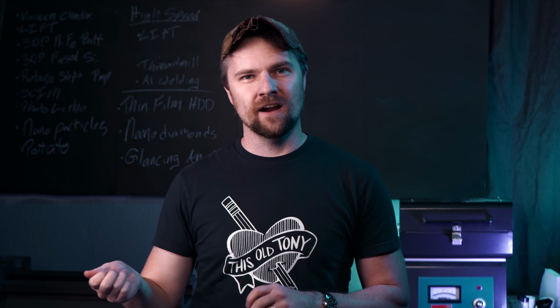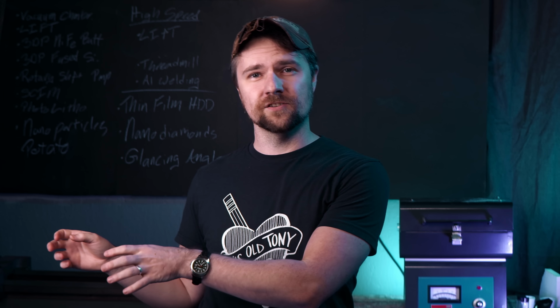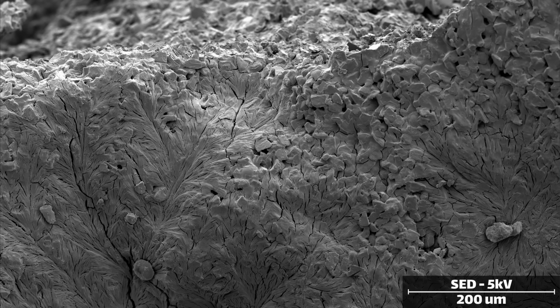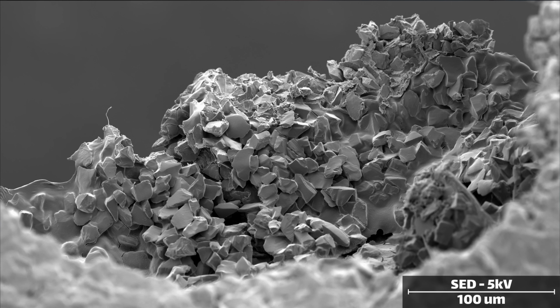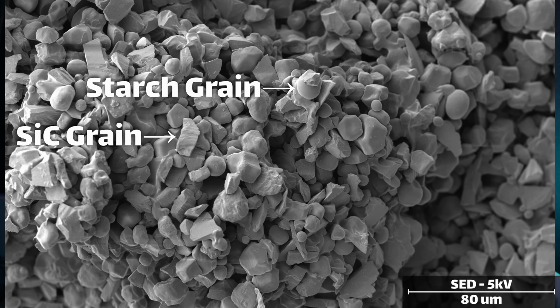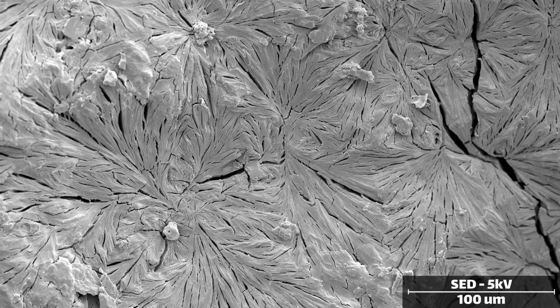I took some of the samples before they were fired and after they were fired and put them in the scanning electron microscope just to see what was going on and if it matched the figures in the paper. Here's a photo of a piece before I fired it. You can see that there are little silicon carbide grains scattered around. They seem to have some type of liquidy network holding them together. That's most likely the borax, which is soluble in water, so it gets spread evenly everywhere. And then long filaments stretching between places, maybe ending in nodules.